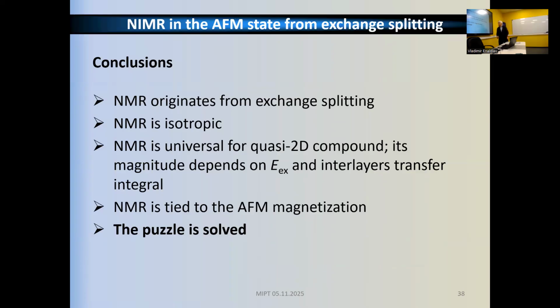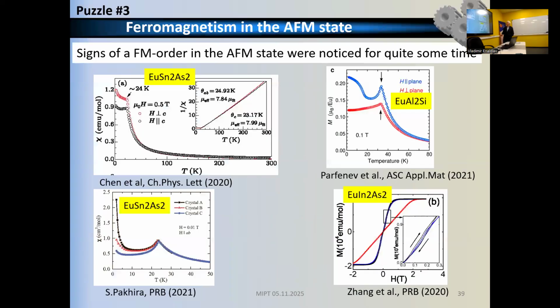And of course, we conclude that the puzzle is solved, at least to the first approximation. Now, the next puzzle is as follows. These nice, pure antiferromagnetic materials, compounds which are well characterized by X-ray, crystal lattice, and so forth, always exhibit some signatures of ferromagnetism, residual ferromagnetism. And it's sample dependent.